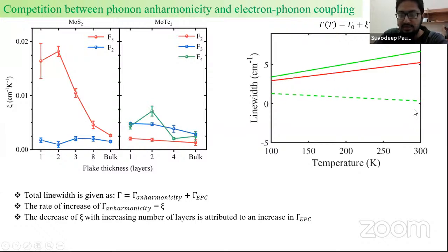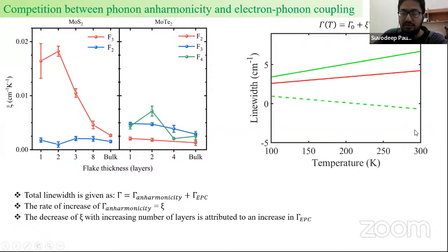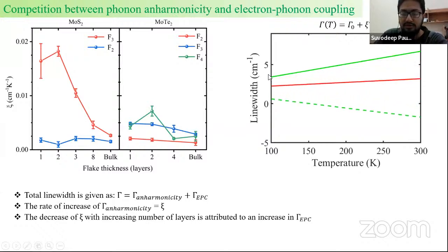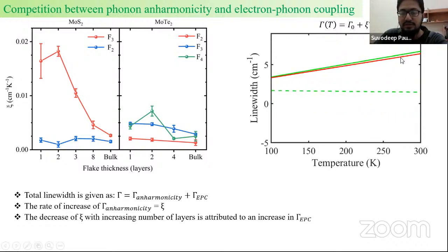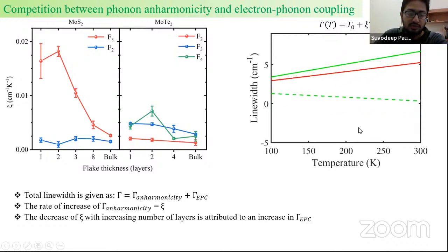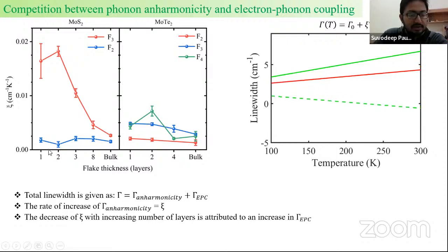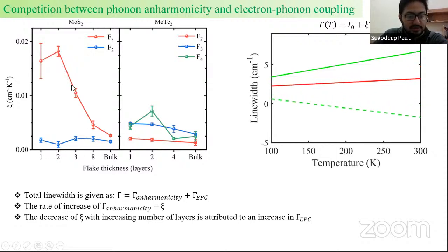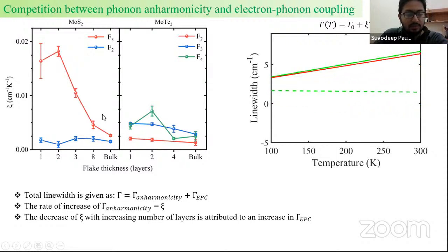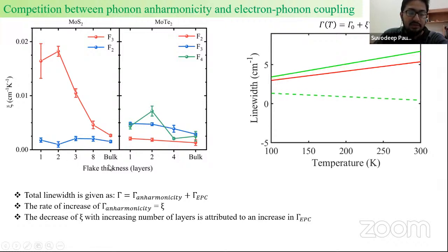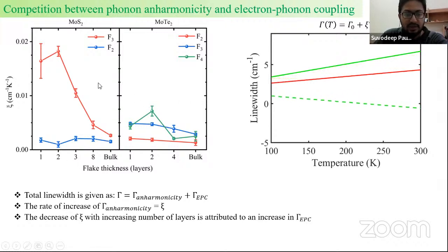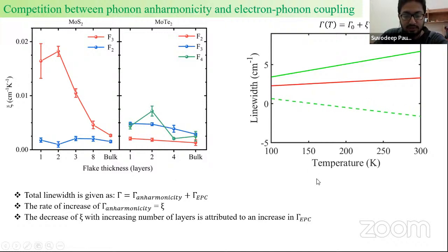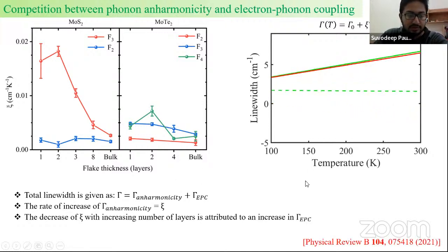We clearly see that by tuning the strength of the electron-phonon coupling, or rather increasing it, we can decrease the effective anharmonic behavior. So the fact that with an increase in thickness, we see a decrease in anharmonic strength may be accounted to the fact that with an increase in thickness, we see an increase in electron-phonon coupling. So further, we have further proof of this.